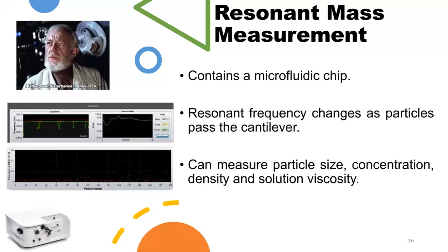The system then uses this change in frequency to calculate the mass of the particle. And since we've already told the computer how dense the particles that it's looking for are, it can then calculate particle diameter. It is also able to calculate particle concentration, solution viscosity, and if I really wanted to, I could simultaneously analyse samples containing both positively and negatively buoyant particles.